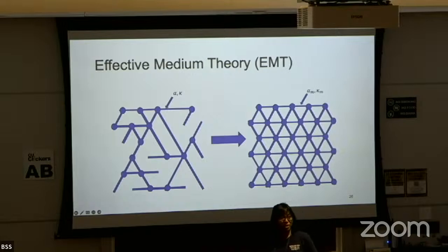So for isotropic networks, these things match up for semi-flexible networks. For anisotropic networks, things are messy and not as clean. I should also mention that people who study granular materials often construct packing-derived networks, which are not networks like I drew them, on a lattice like this. If you construct packing-derived networks from granular materials, the shear modulus and bulk modulus percolation thresholds for rigidity do not necessarily match up. But for biopolymer networks like the ones we are thinking of here, they will match up.